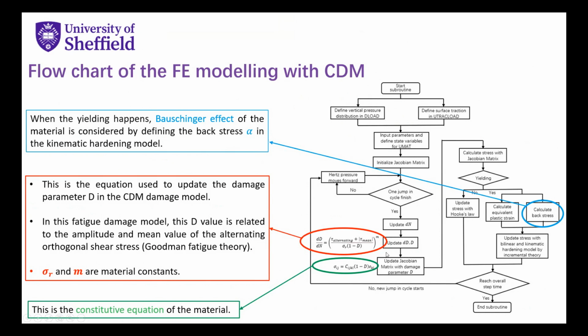As you can see in the right circle here, this is the equation I used to update the damage parameter D in the CDM damage model. In this fatigue model, this D value is related to the amplitude and mean value of the alternating orthogonal shear stress. The reason why I use this amplitude and mean value of the stress is based on the Goodman fatigue theory, because it believes the fatigue behavior of material is related to the stress level and the mean stress of the overall loading. That is why I use these two stresses here to calculate the damage value. Sigma r and m here are material constants which can be determined from the SN curve of the material.